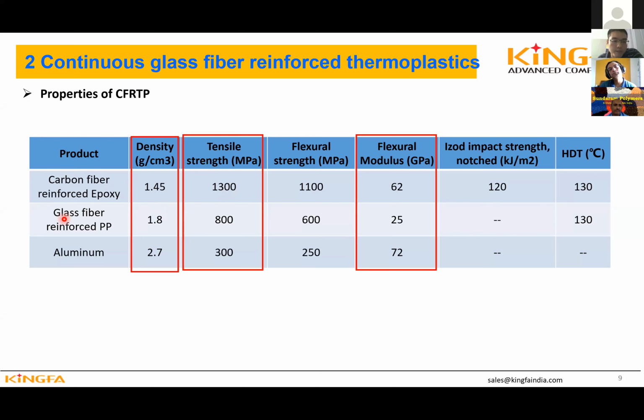So we can choose to use glass fiber reinforced polypropylene. The property is a little lower than the carbon fiber reinforced epoxy, it's 800, and the density is increased a little, it's 1.8. If we compare this material with aluminum, it also has some advantages in strength and low density. The only disadvantage of this material is the flexure modulus is only 25 GPa, which is much less than aluminum, but we can make some structure design, then we can make the part meet the requirement.